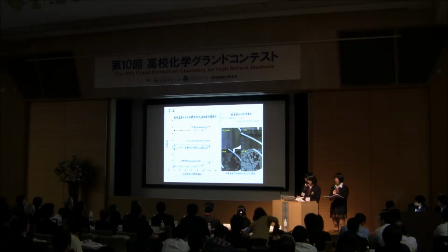The weight of solute in the water increases slowly, so the limestone in the tank was dissolved. But we were not able to reproduce the block of CaCO3. 6 days after, we stopped the injection of CO2. A lot of CaCO3 appeared on the water surface in the water tank.